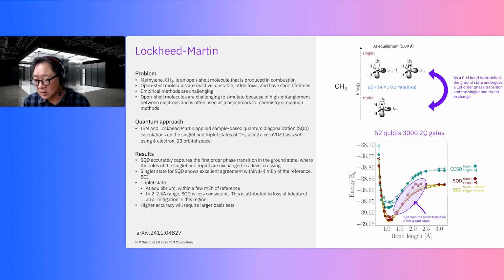Above around 2 angstroms, you can see the SQD singlet solutions are again very close to SCI. The triplet state is doing something funky. We know that this is incorrect. It's about tens of millihartrees away from the reference here. And what's going on is we have a loss of fidelity in the error mitigation. We think we know what's going on. One way to address this will be higher accuracy, which will be larger basis sets. In other words, we need to do this with more qubits on the quantum computer. There's another funny thing, the way we mapped it to our particular quantum computer, where we think future processors will also be able to solve this.